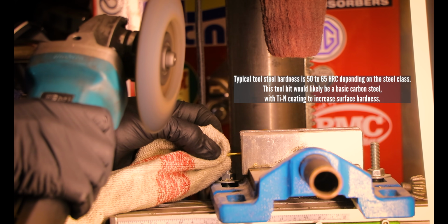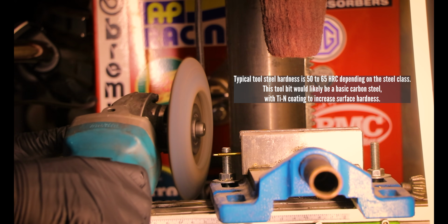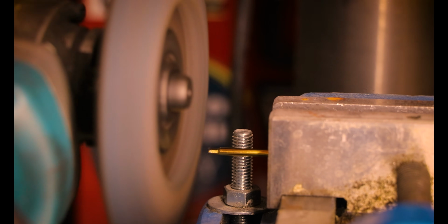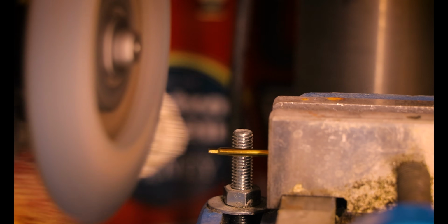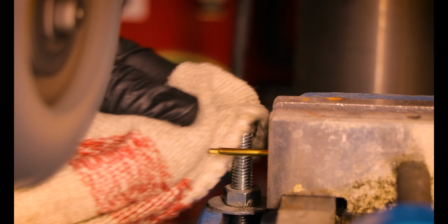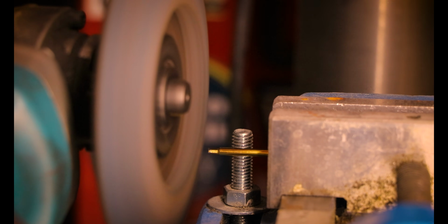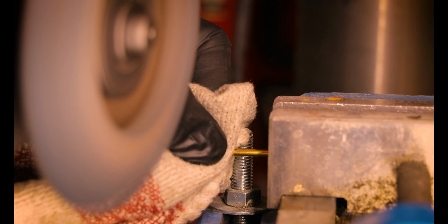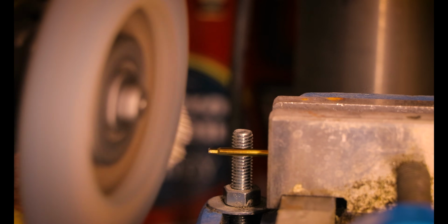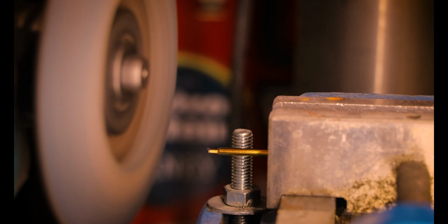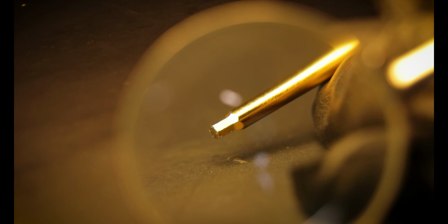We need to remove material to get back to fresh geometry while managing the metallurgy so we stay in the 58 to 60 Rockwell C hardness range. I'm grinding back about 1.5 mm to remove the damaged material. Short bursts, quench with a wet rag. Rinse and repeat.